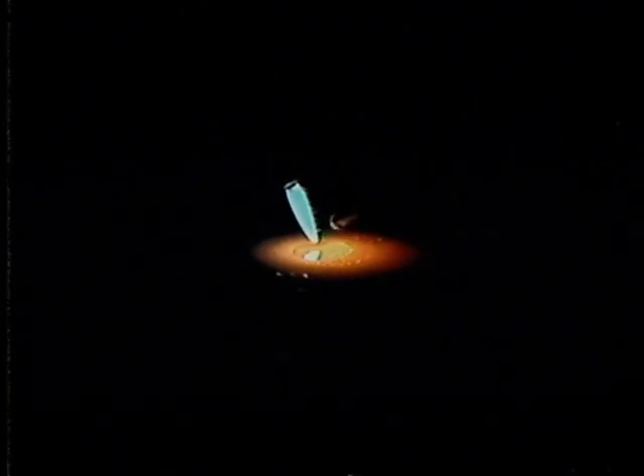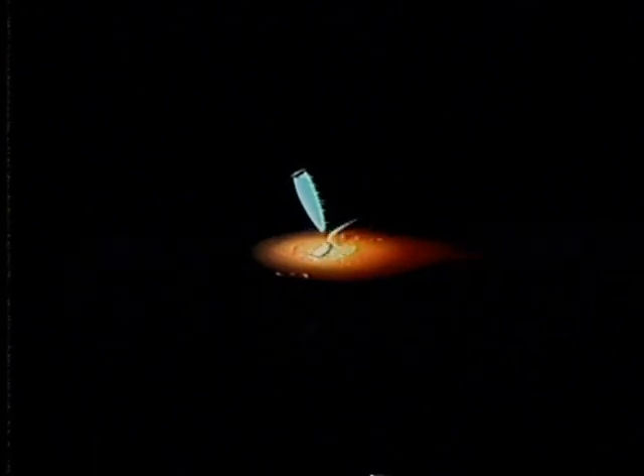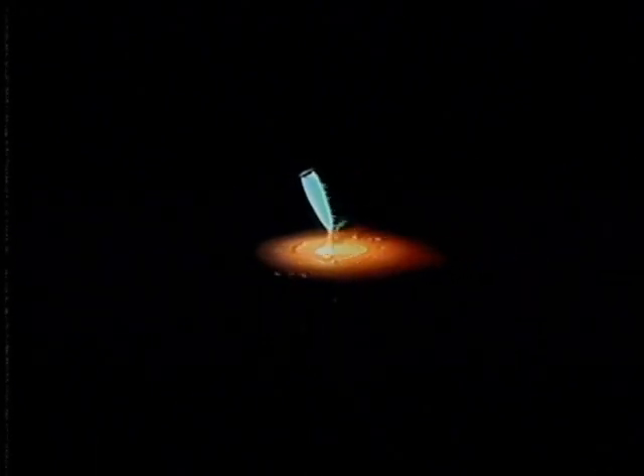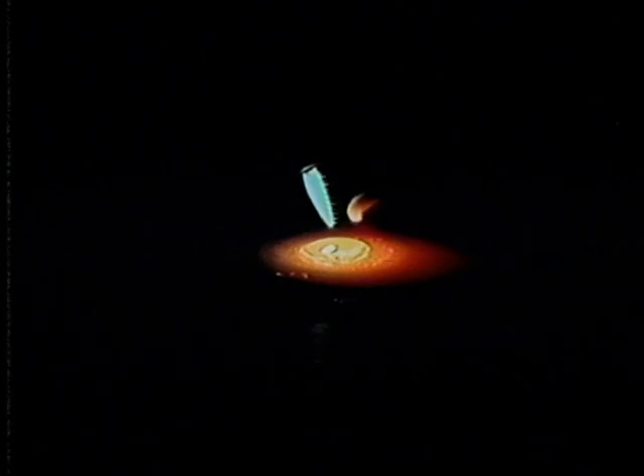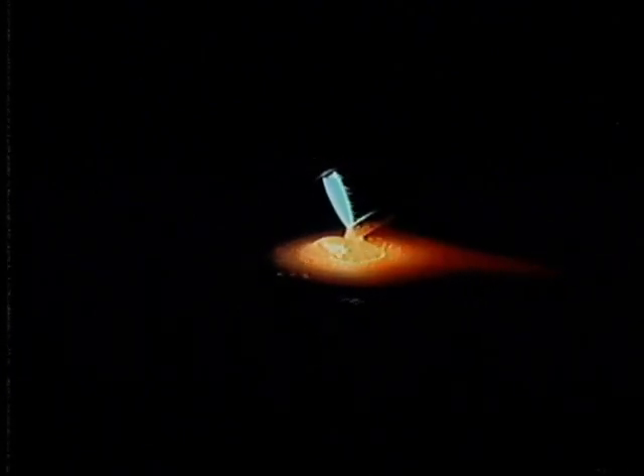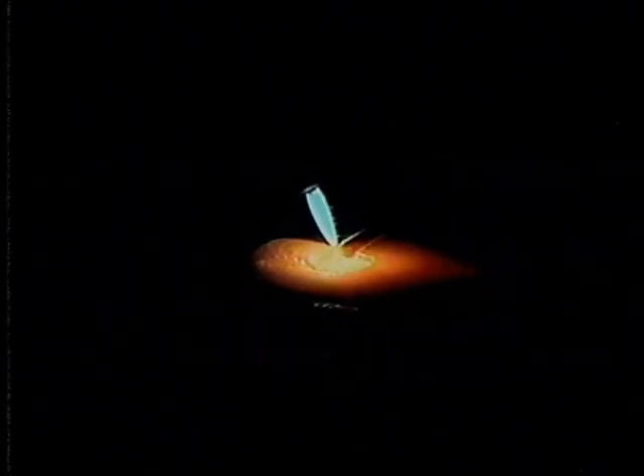Now you notice here that he adds the filler to the puddle and that he removes it just a little bit. He's still in the secondary flame with that filler. If he pulls that filler too far away from the puddle, he will cool it off, and when he places it back into the puddle, it will actually chill the puddle and cause a cold weld. Why couldn't he melt the filler rod with the flame? If he melts the filler with the flame, it merely lays the bead on top and you don't get any penetration with it. So you must actually establish a puddle and then add the filler to that puddle. It would just lay on top and you wouldn't get a good weld. That's right. You wouldn't have penetration, you wouldn't have a sound weld.